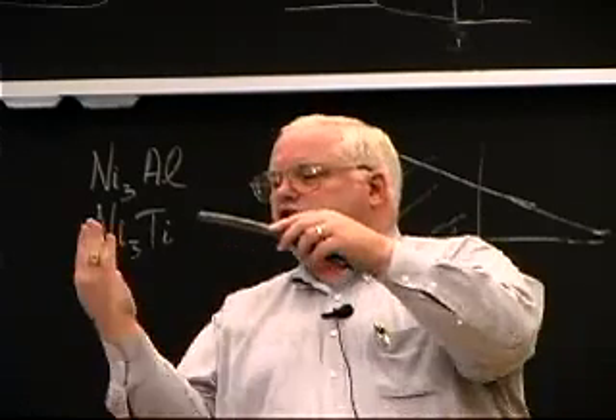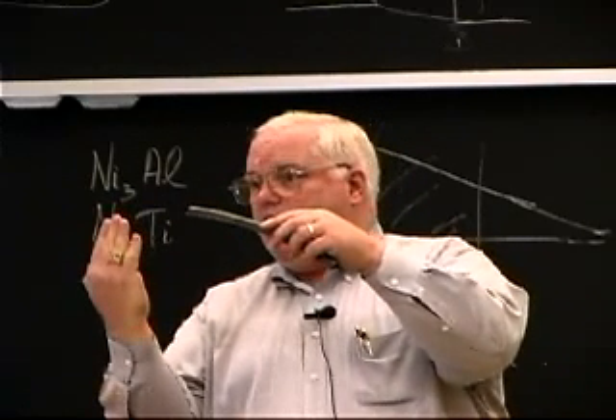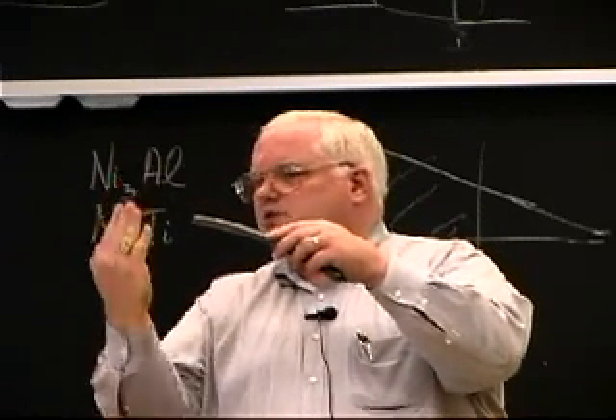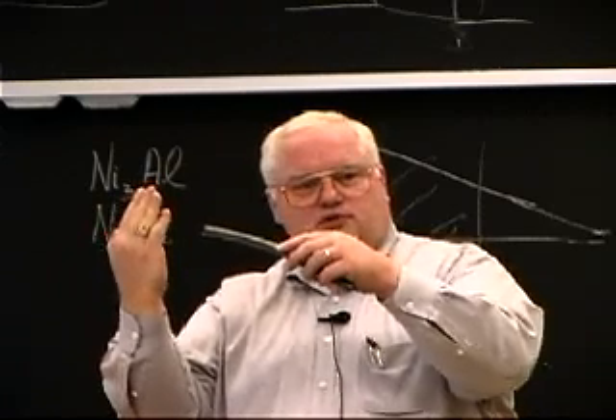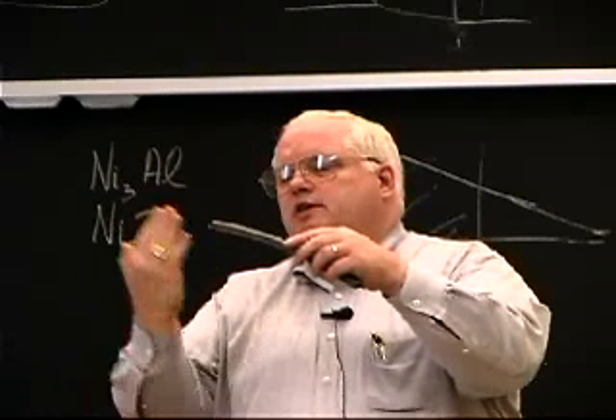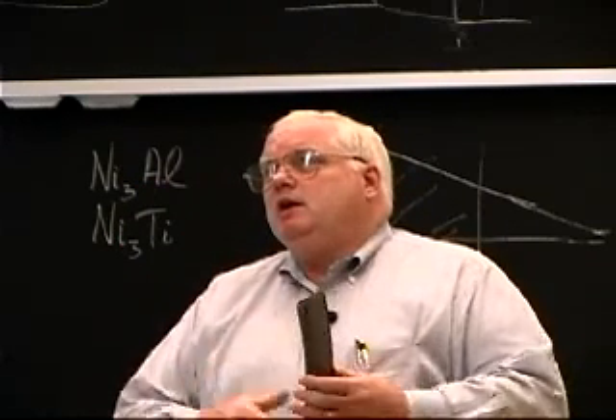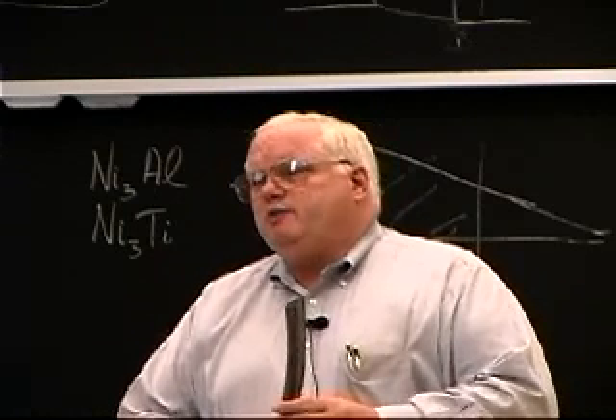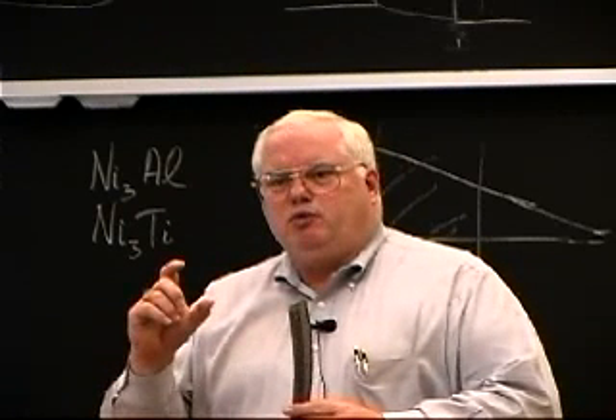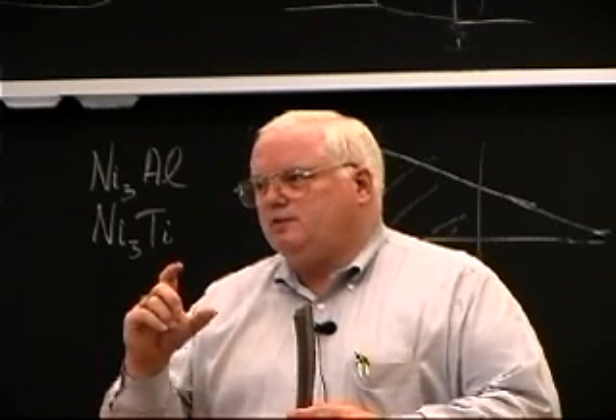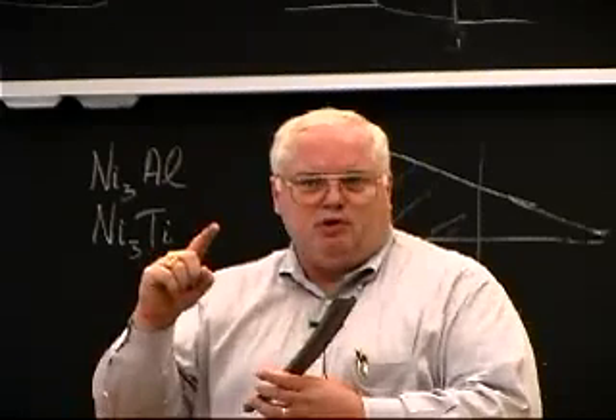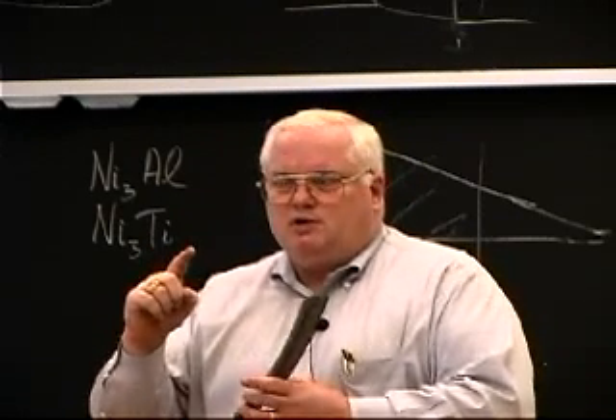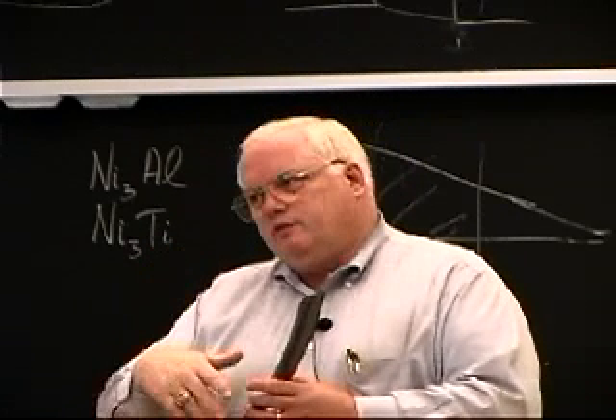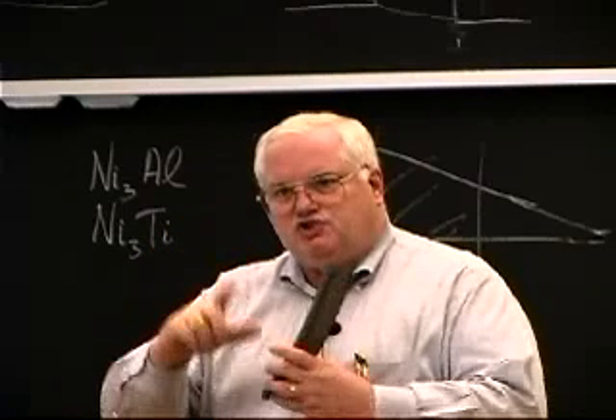And as the turbine blade ages, it's hot, it will actually grow in length because it creeps, right? It's under stress, centrifugal stress, and it's hot, and it will creep over time. And typically, I think they're allowed like 3% growth over the life of the blade. And so they actually have specs. You measure the length of the blade when it comes back, and if it's within a certain limit, you can repair it, and if not, you got to scrap it because it's already stretched too much.